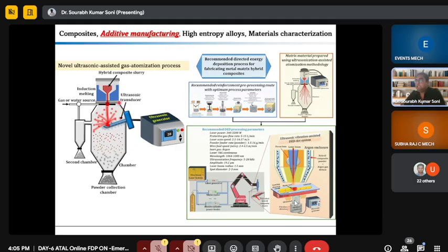So based on the literature review, I recommended this novel ultrasonic assisted gas atomization process. So with this kind of novel ultrasonic assisted gas atomization process, we can prepare the composite powder. Nowadays, what we are doing, we are preparing the powder through the gas atomizer, but we can prepare the composite powder also by using this gas atomization process.